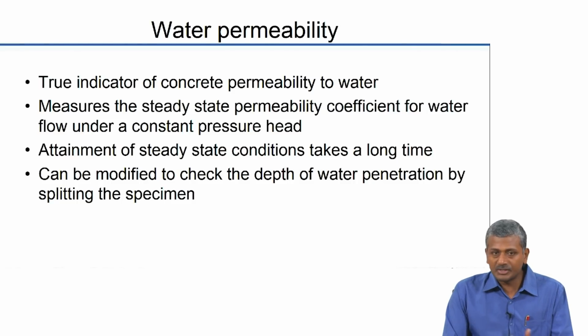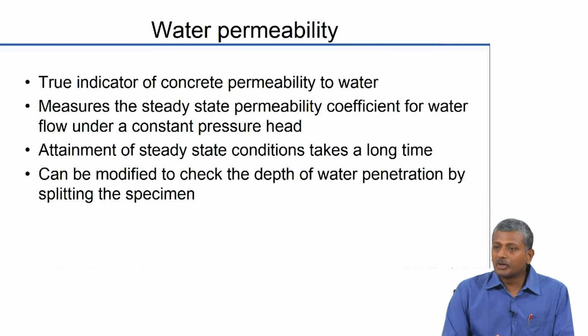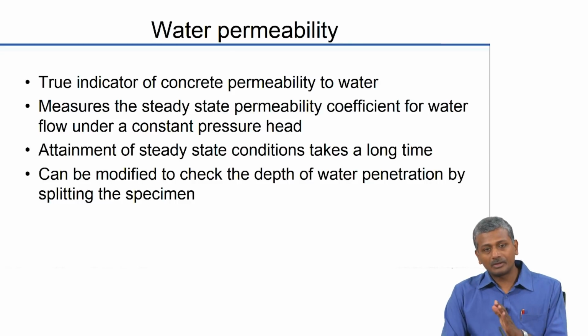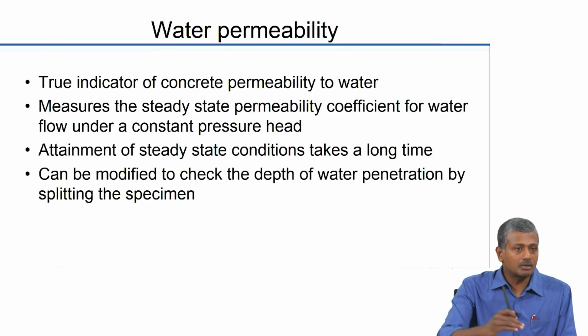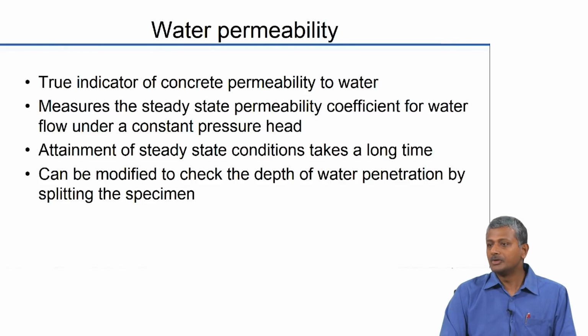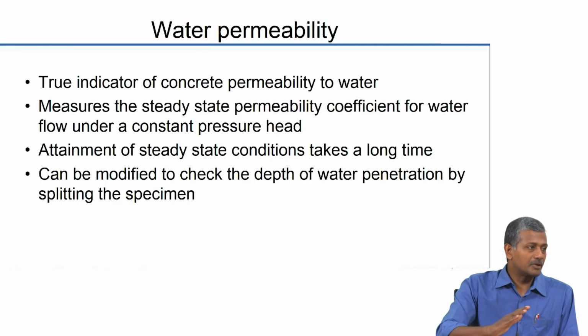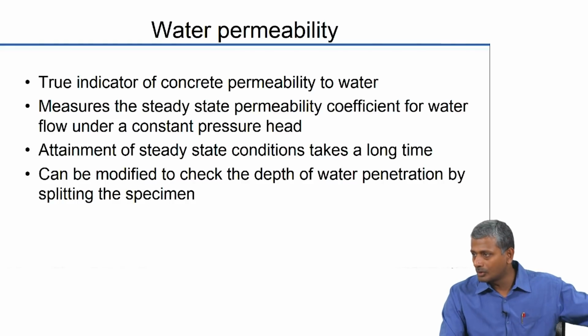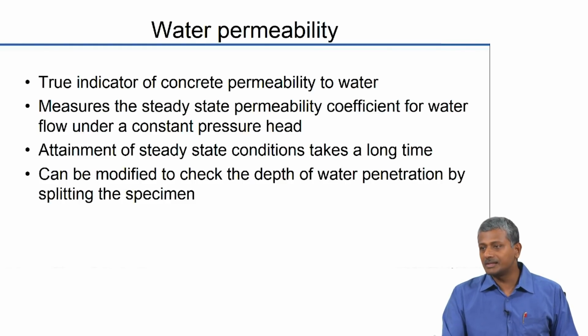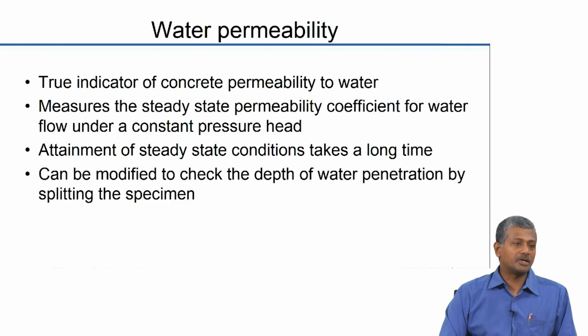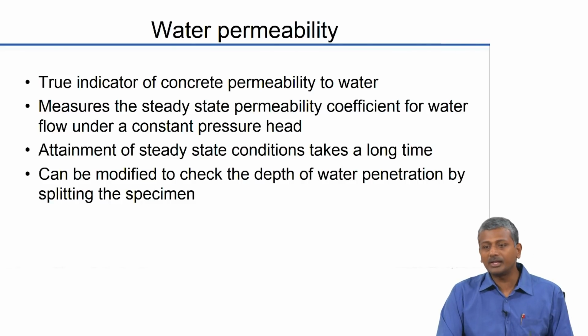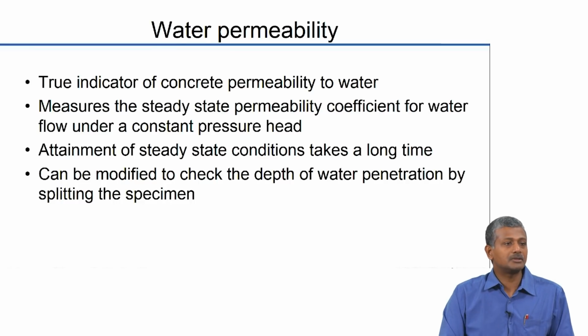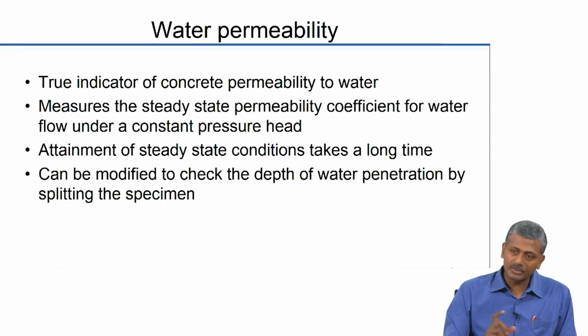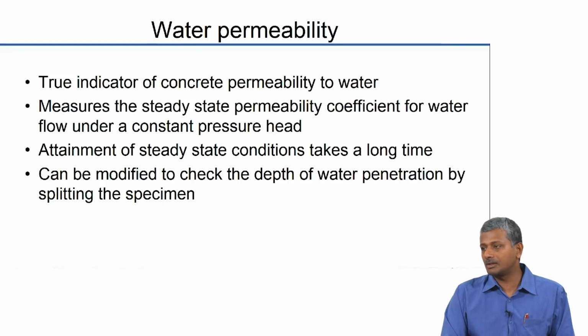Now, you know very well, as we just discussed, attainment of steady state takes a long time. So because of that, this test has been suitably modified by different standards to not just look at the flow at the other end, but stop the test when the water has penetrated the concrete by a certain distance. For example, you apply the same pressure, but instead of making the water penetrate the entire distance and flow out of the concrete, you stop the test after 2 or 3 days, split the concrete open, and measure the depth of water penetration and use that as an indicator of durability. The only difficulty there is you can't apply any law to determine the permeability coefficient. You only have an arbitrary parameter that is equal to the depth of water penetration, and you use that as a durability characteristic to classify the concrete.